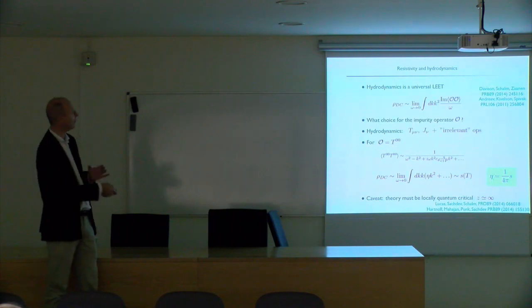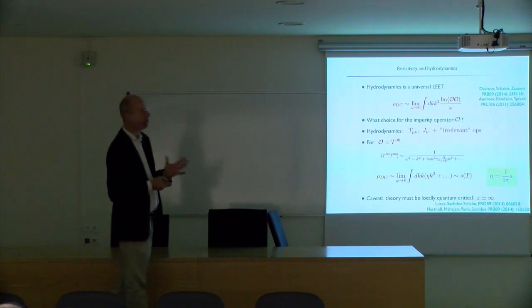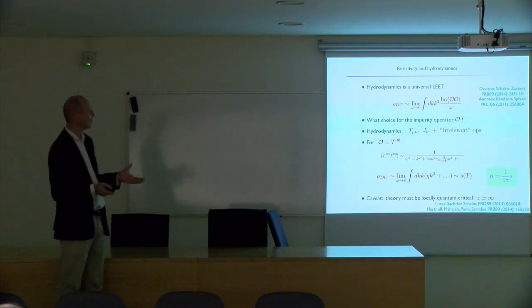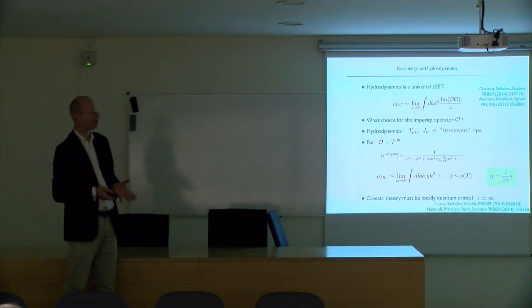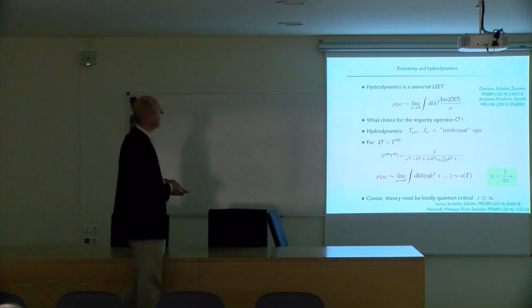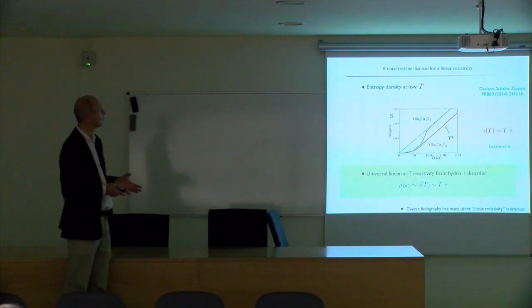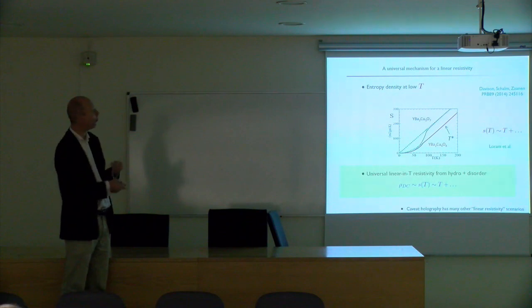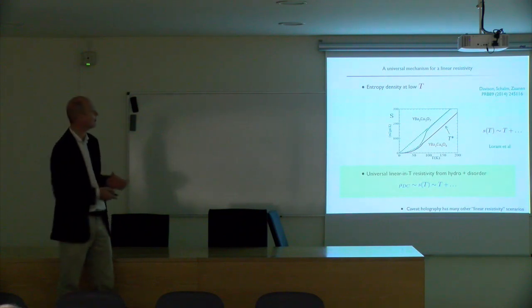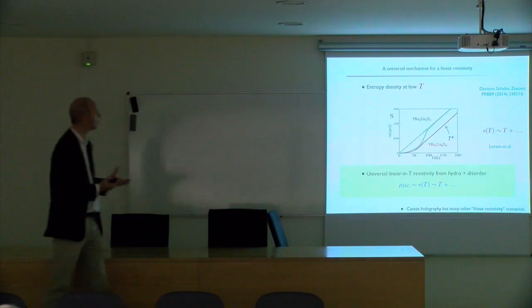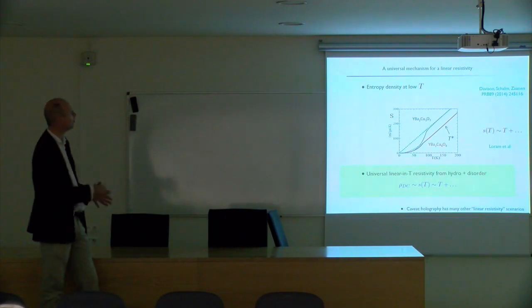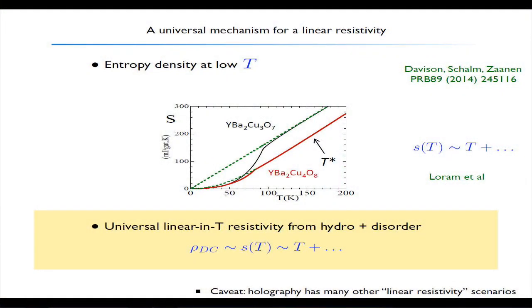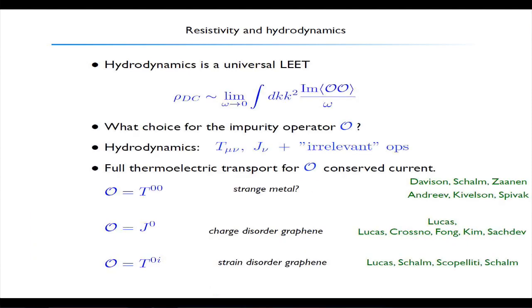And then you need one ingredient from holography that tells you that the shear viscosity is very often proportional to entropy density. And you find a sort of phenomenological formula that the resistivity is set by the entropy density in the system. This is a very simple but beautiful universal result that may explain precisely why these systems display a linear in T temperature dependence. Because one of the things that happens is that in almost all these systems, you find that the entropy density does grow linearly with T. It's called the Sommerfeld law. In an electron system, you can compute it, but also these high Tc cuprates have this behavior that the entropy density at low temperatures is linear in T.